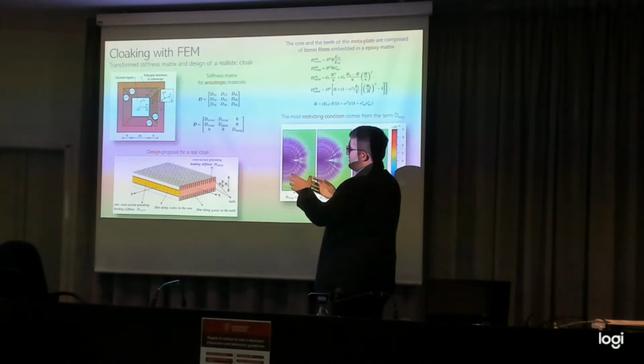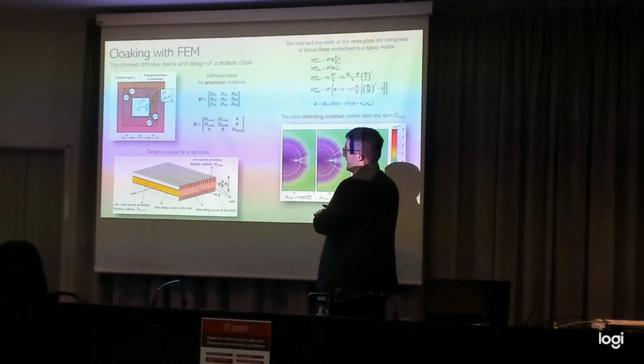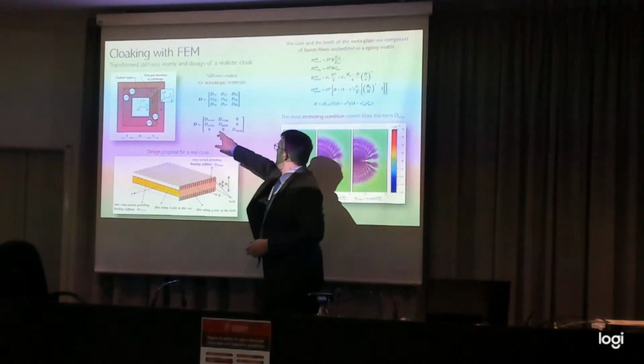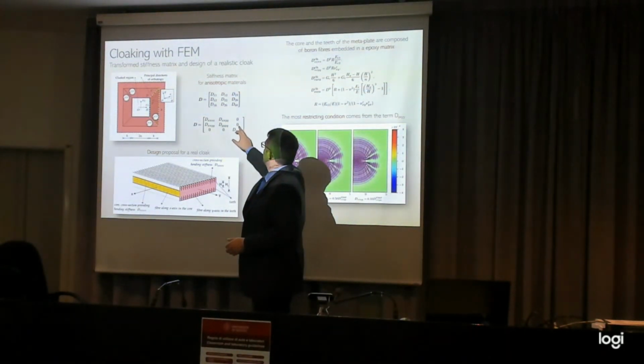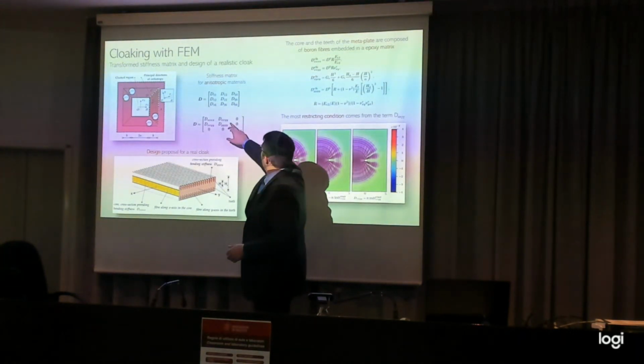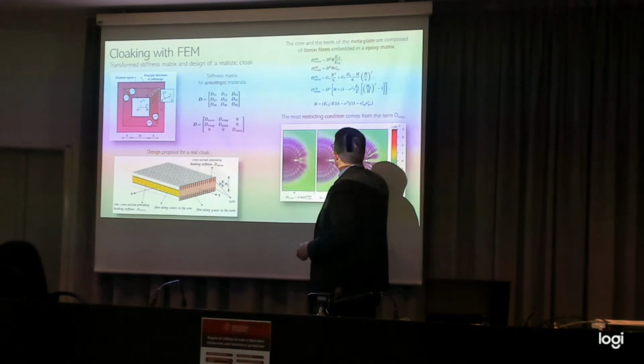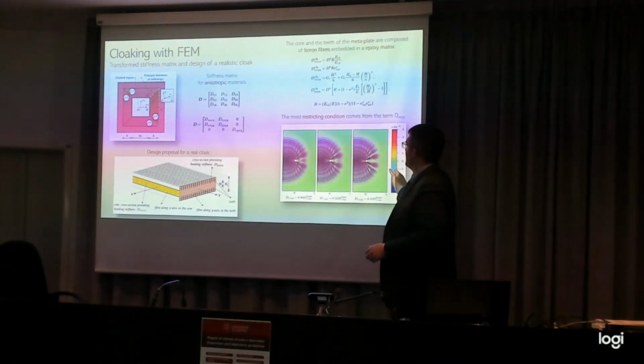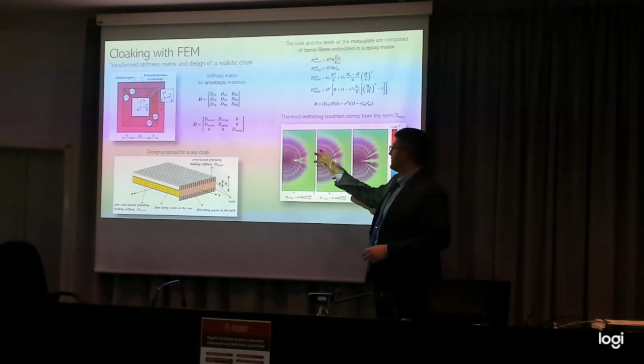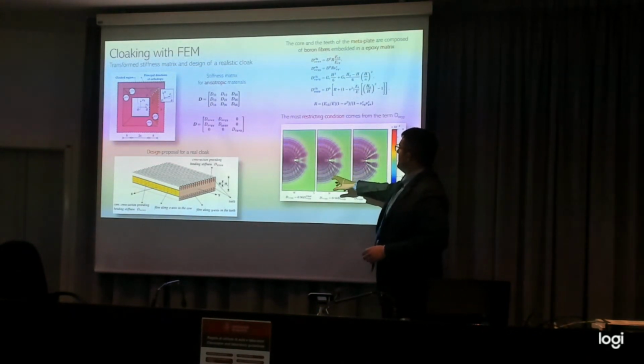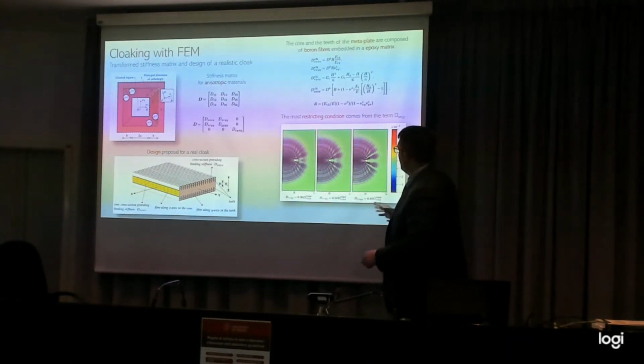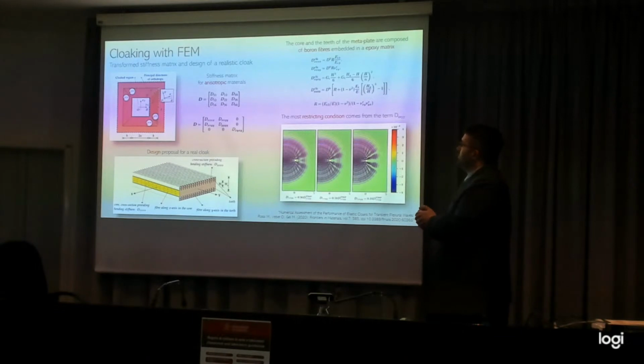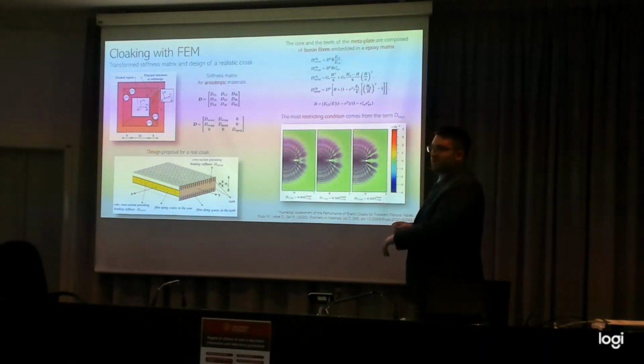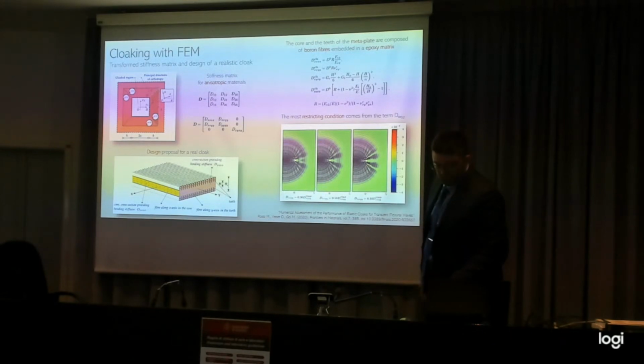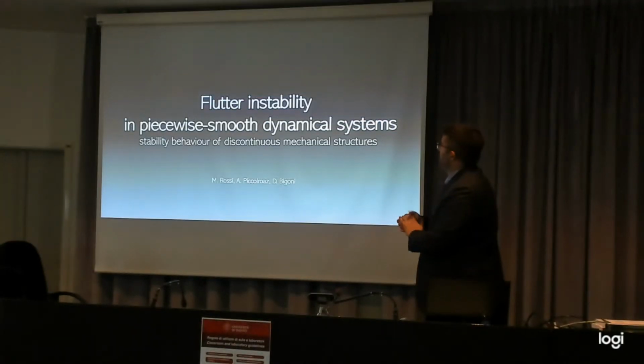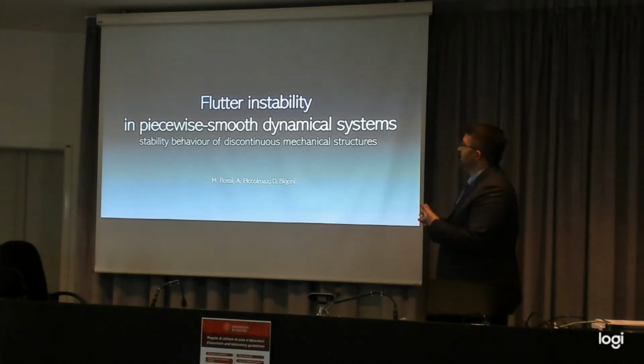We discovered that it's possible to tune all the parameters of the plate, the geometrical parameters, in order to fix those two components and reduce as much as possible this one. Then at the end we discovered that also this term is important. As you can see here, also here you can see the detrimental effect of having a D_xxyy, the term which is outside the diagonal, which is not the one predicted by theory. So this must be investigated maybe in future works in order to understand better how to design a proper invisibility cloak.